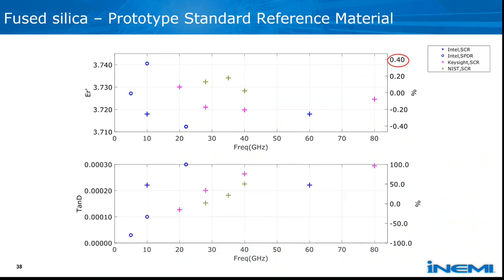Really, the thing I'm trying to highlight is that we had an overall spread of about plus or minus 0.4% if we're all using the same thickness, which is really, really narrow and great for showing we have high reproducibility. But the disclaimer is, again, we're all using the same thickness measurements, and most of these are made with SCRs from the same vendor.